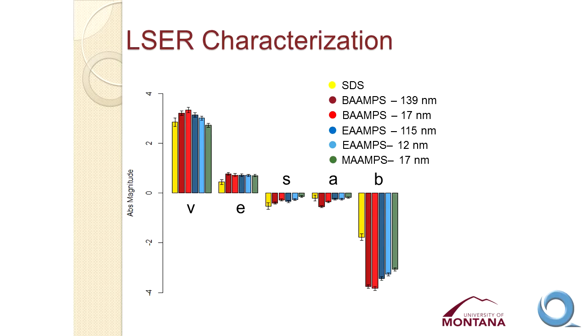And in fact, if we apply our linear solvation energy relationship model to these materials, looking at butyl acrylate, ethyl acrylate, and methyl acrylate polymers, all with the same AMPS shell, and with different sizes, what we see is actually some trend in these results. So going from larger nanoparticles towards smaller nanoparticles and going from longer alkyl chains towards shorter alkyl chains, we see that the nanoparticles become more cohesive, less able to solvate large molecules. We also see that these compounds become more able to interact with basic compounds, more able to interact with acidic compounds, and more able to interact with polar compounds. So we see some trends in the results.